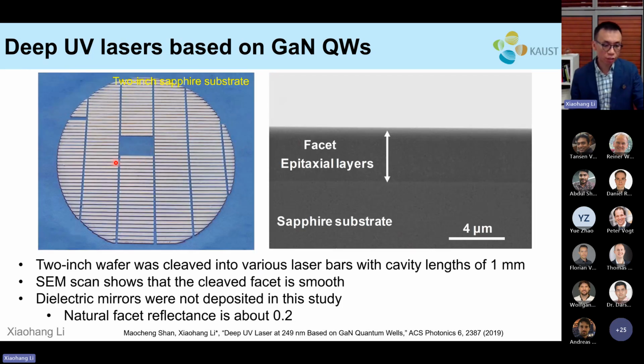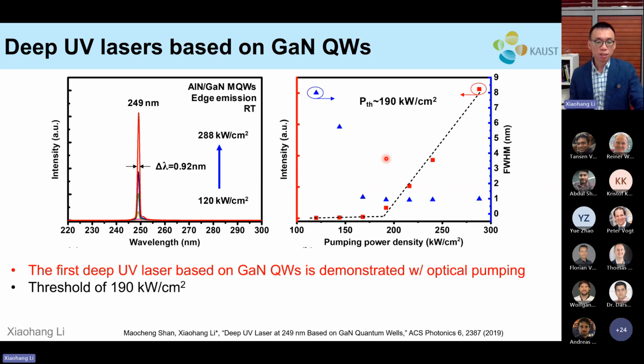Then we cleave the 2-inch wafers into different laser bars. From the SEM, the cleaved facet is very smooth. We did not apply dielectric DBR mirrors here, so we have a natural facet reflectance of about 0.2 for UVC wavelengths. With photo pumping, we demonstrated the first deep UV laser based on gallium nitride quantum wells. At pumping power above the threshold, we have a narrow linewidth of about 0.9 nanometer, and on the right you have the L-I curve indicating the laser operation. The threshold is about 190 kilowatts per centimeter squared.